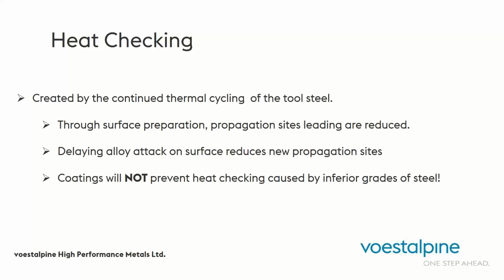Now, common practice has been in the past to draw polish the surface, and there's a lot of reasons. There's a lot of theories for doing that, but we've proven that a draw polish is not required. And in fact, it can be detrimental. In particular, draw polish is detrimental to applying coating. I don't recommend you apply coating to a draw polish surface.